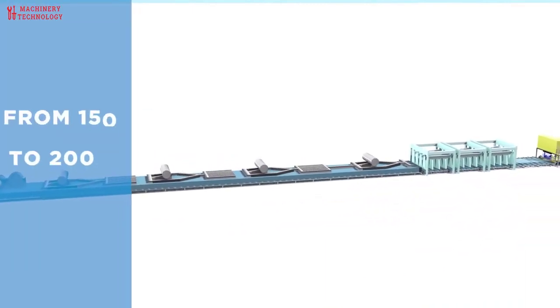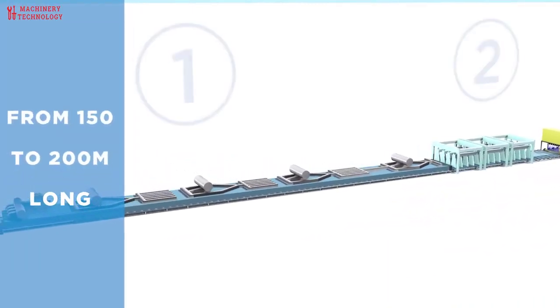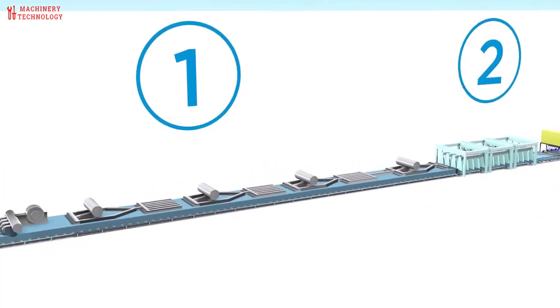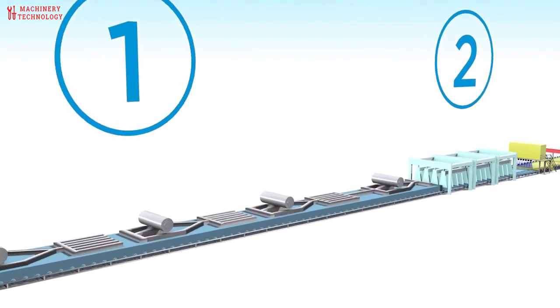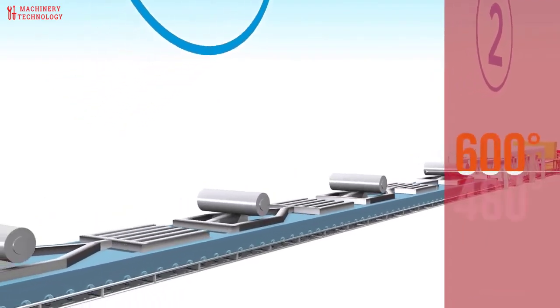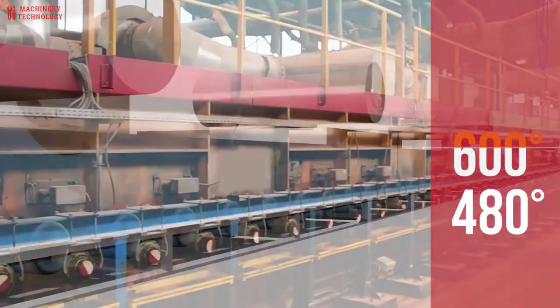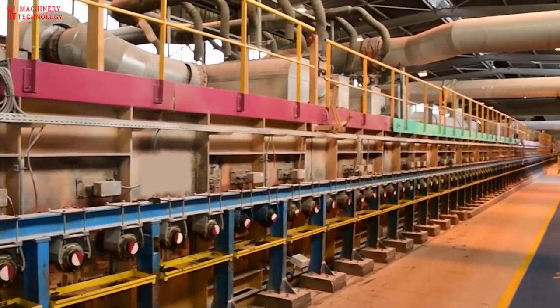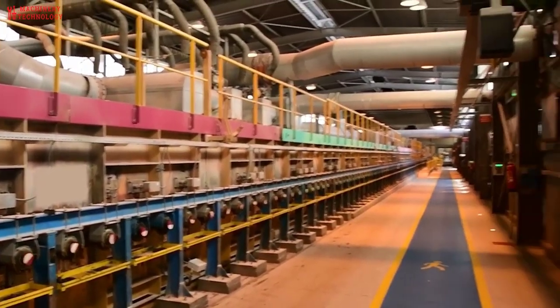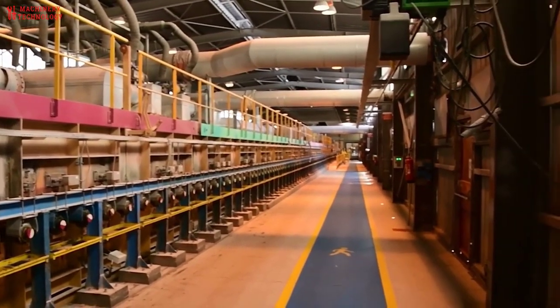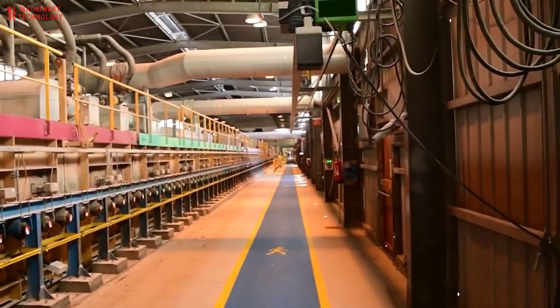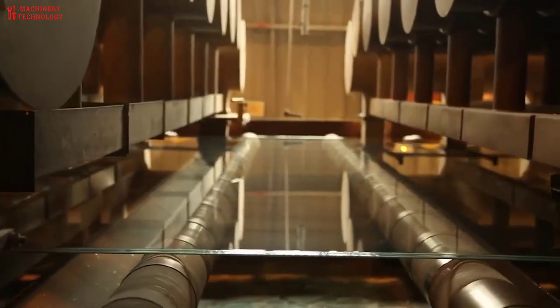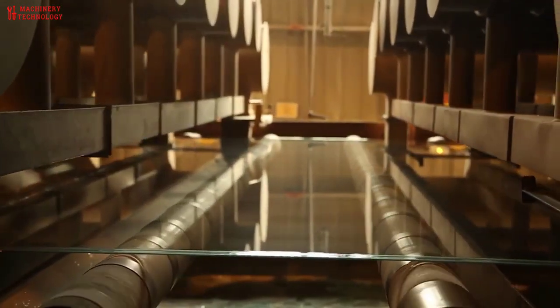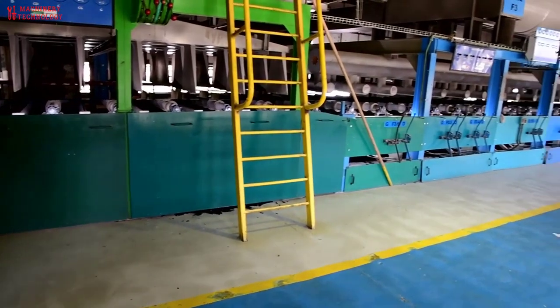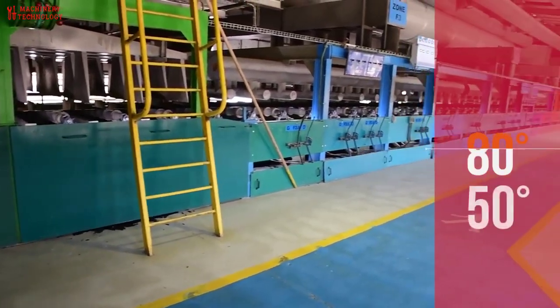The lehr measures from 150 to 200 meters long and is made of 2 parts. The first one is the annealing zone, where the temperature decreases from 600 to 480 degrees Celsius and where permanent stress is fixed. This is a critical part of the process to give the glass a cutting quality that matches customers' requirements. The second part of the lehr is the cooling zone, where, depending on its thickness, the ribbon is gradually cooled to reach a temperature between 50 degrees Celsius and 80 degrees Celsius.